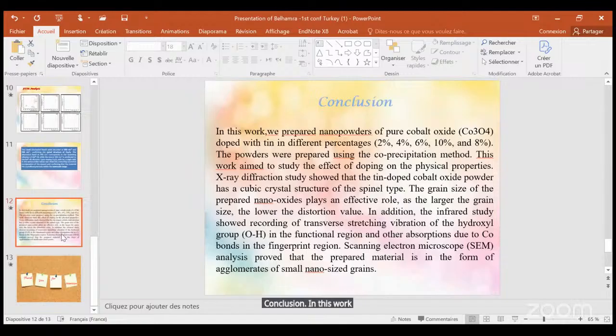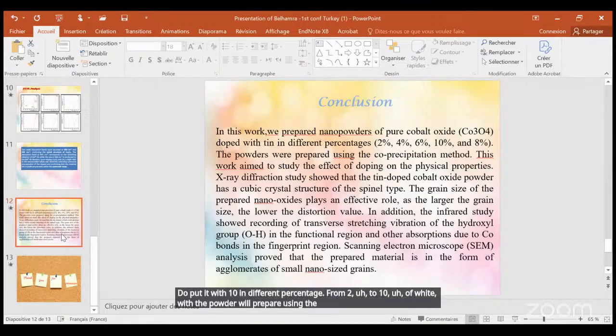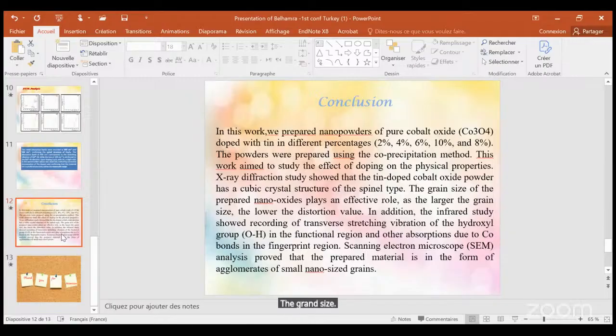Conclusion: In this work, we prepared nanopowder of pure cobalt oxide doped with Sn in different percentages from 2 to 10 percent by weight. The powders were prepared using the co-precipitation method, and the work aimed to study the effect of doping on the physical properties. X-ray diffraction study shows that the Sn-doped cobalt oxide powder has a cubic crystal structure of the spinel type. The grain size of the prepared nano oxide plays an effective role: the larger the grain size, the lower the distortion value.